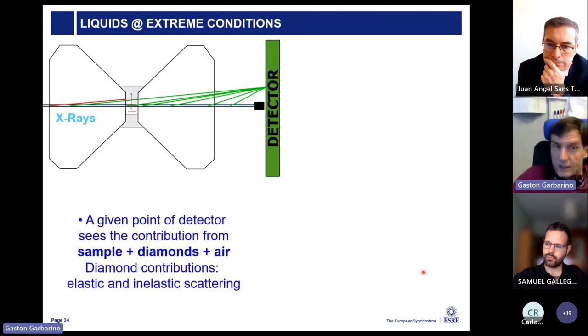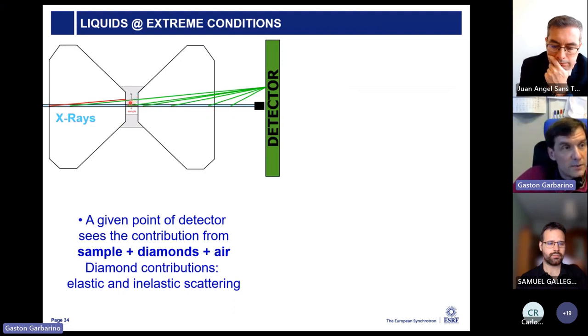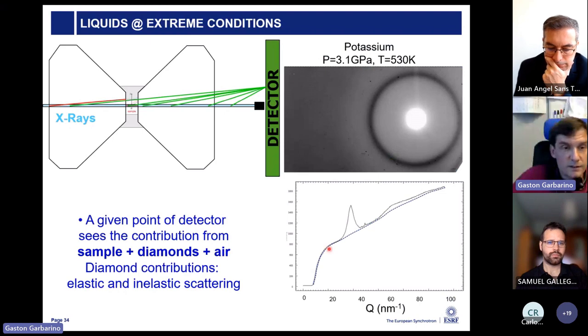And one last example that I would like to show you, because it was interesting at the beginning, is how to study liquids at extreme conditions. So as we said, the X-ray beam is passing through the sample. So the sample is sitting here and is surrounded by these two diamonds. And the thing is, as soon as the beam is passing through, you will have not only diffraction coming from the diamond, but also you will have Compton scattering. So this will be a kind of diffuse signal. So it can be seen like this.